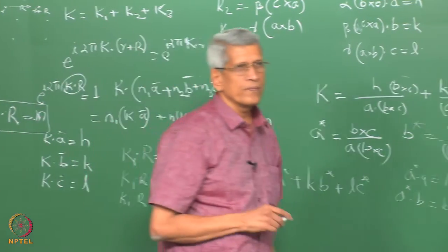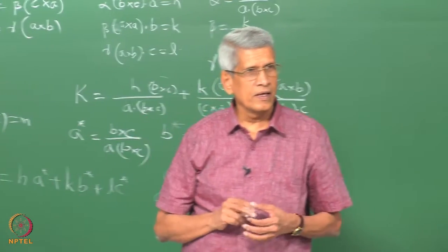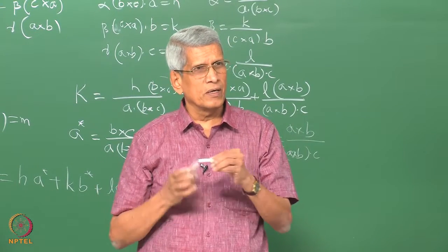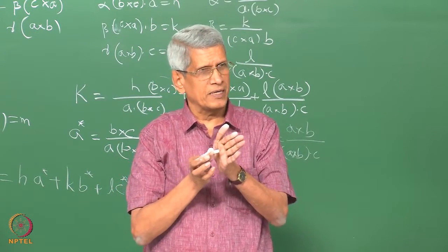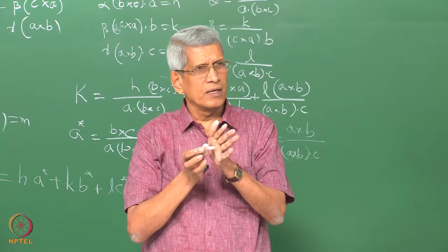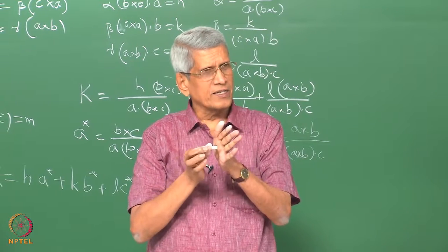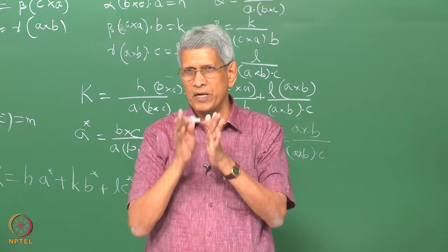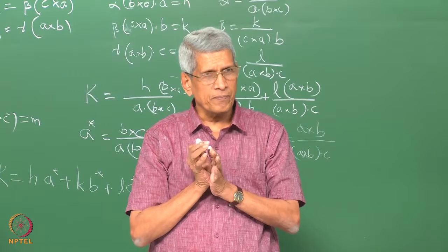What does it mean? For a particular value of k1 which has been chosen, k1 is normal to a particular plane, with a magnitude which is the inverse of the interplanar spacing between those planes.